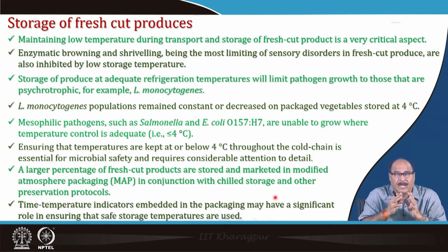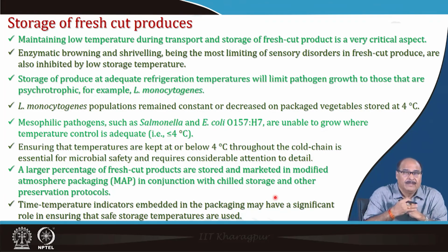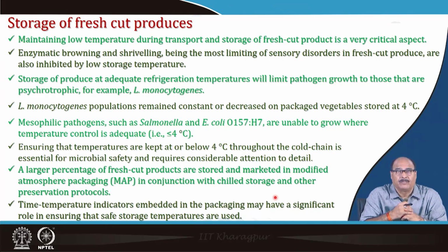Storage of produce at adequate refrigeration temperature is even reported to limit pathogenic microbial growth also, particularly those which are psychrotrophic, for example L. monocytogenes, etc. Their growth will be suppressed if the temperature is less than 4 degrees Celsius. In fact, L. monocytogenes populations in some experiments remained constant or decreased on packaged vegetables when stored at less than 4 degrees Celsius. Mesophilic pathogens like Salmonella and E. coli are unable to grow where the temperature control is adequate, that is less than 4 degrees Celsius. Ensuring the temperatures are kept at or below 4 degrees Celsius throughout the cold chain is essential for microbial safety, and it requires considerable attention to detail.